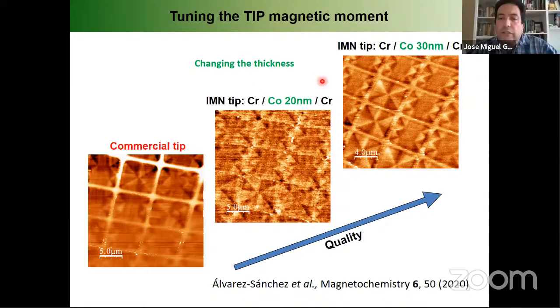And do you have any problem with stability of the measurement, like with electric charge or something, or not? When you measure, no, this is quite stable, as you can see here. But of course, with commercial tips, in the case of the antidots, it was impossible to distinguish the magnetic domain state because the tip was perturbing a lot.